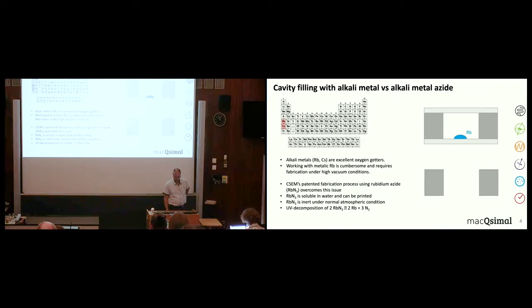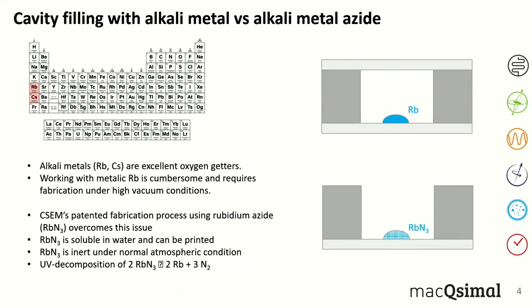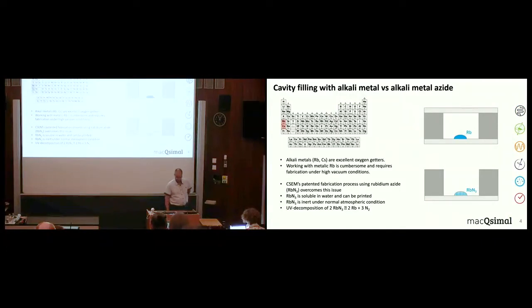So that's why we came up with another idea. We still start with a silicon wafer where we etch a through hole. We put a glass wafer on the backside. But now we do the filling, instead of metallic rubidium, with rubidium azide. Rubidium azide is a salt. It is very well soluble in water and can then be printed or spotted. And the big advantage of working with rubidium azide is that this salt is completely inert under normal atmospheric conditions, so it will not react with oxygen.